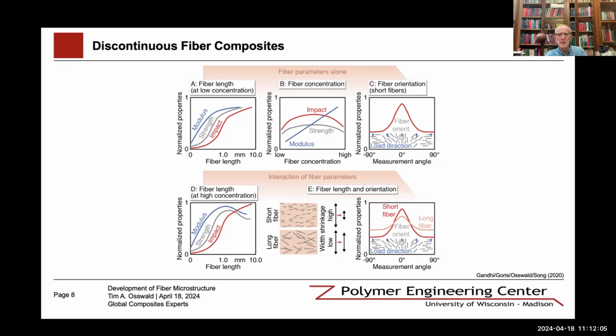There's, of course, interactions between all of those, between the fiber density, fiber orientation, fiber length. So fiber length will, of course, at high concentrations, start going down. The modulus eventually goes down. In the middle, you will have shorter fibers, longer fibers, and they will affect orientation on the right-hand side of the lower part, where the long fibers will reach lower degrees of orientation because of higher interactions between the fibers. Short fibers, of course, will be able to reach higher degrees of orientation.